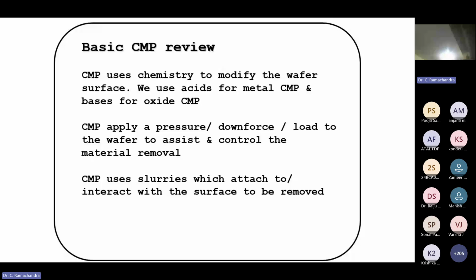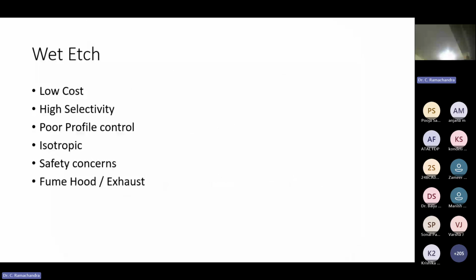So wet means it is a liquid, a chemical, basically. The advantage is very, very low cost. The biggest advantage is high selectivity. That means if I want to etch silicon dioxide but not silicon nitride, I can choose a proper chemical. I want to etch aluminum but not silicon dioxide, I can choose a chemical. So chemicals provide very high selectivity. So if selectivity is the criterion, this is the best method available, and low cost.